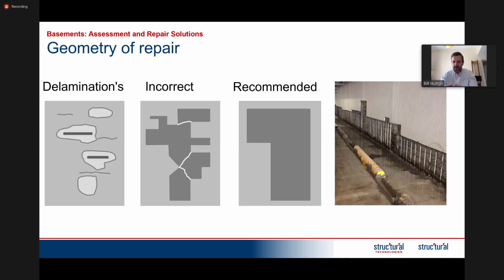Now, the challenge is that if you repair in that complex shape, you have a lot of inclined corners, and there probably will be a slightly different thermal coefficient of expansion between the repair material and the native concrete. If they're expanding and contracting at slightly different rates, then if you have a complex shape, you're more likely to have cracks in your repair. And obviously wherever you have cracks, the steel is exposed and your repair may fail. So it would be better to go for a simple geometry with as few corners as possible.